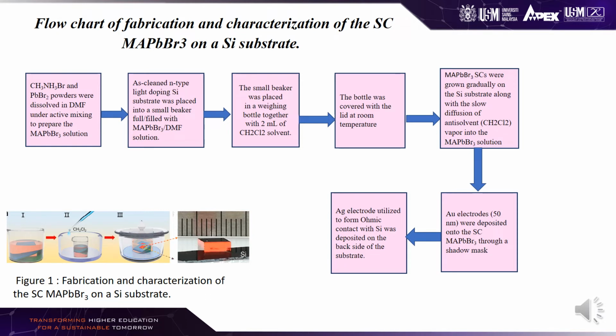Next step, MAPbBr3 single crystals were grown gradually on the silicon substrate along with the slow diffusion of anti-solvent CH2Cl2 vapor into the MAPbBr3 solution. Next, the gold electrodes of 50 nanometers were deposited onto the single crystal MAPbBr3 through a shadow mask. Finally, the silver electrode utilized to form ohmic contact with silicon was deposited on the backside of the substrate.